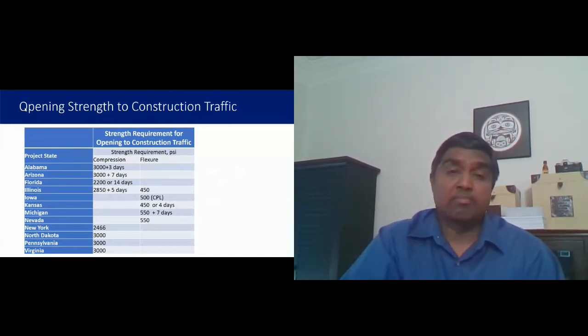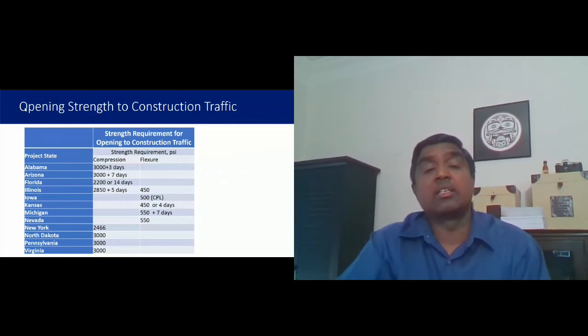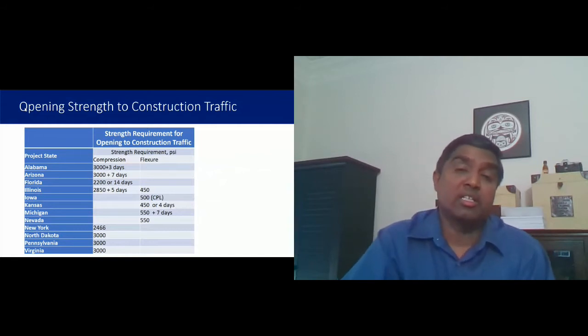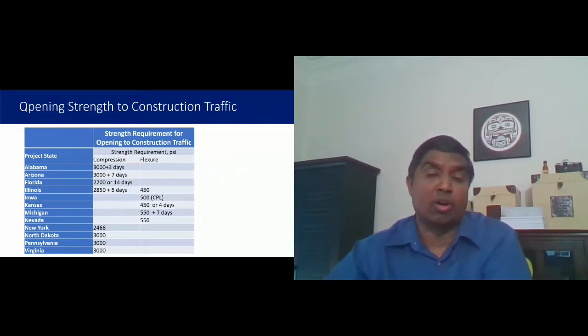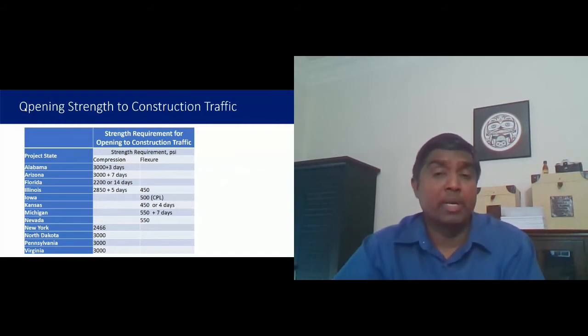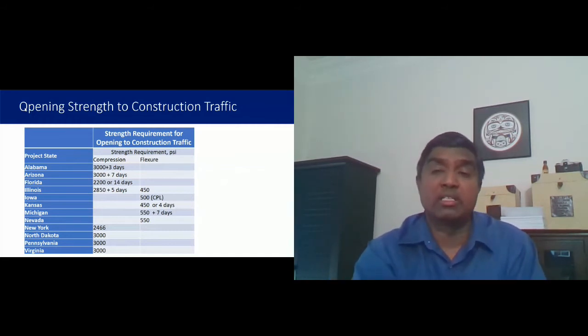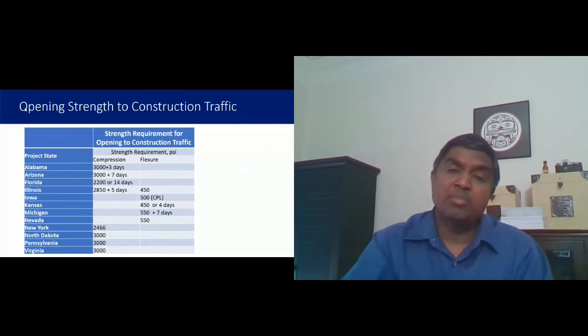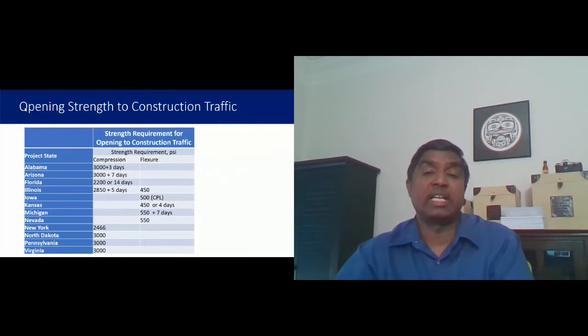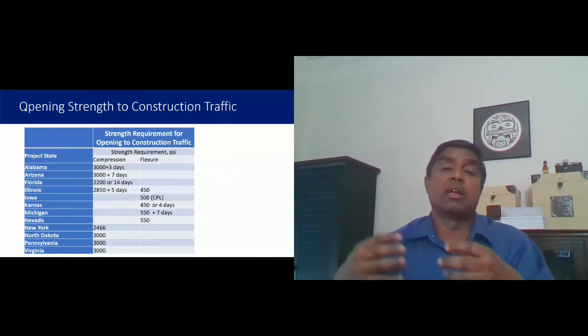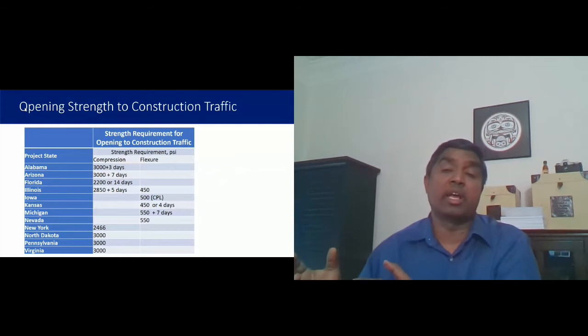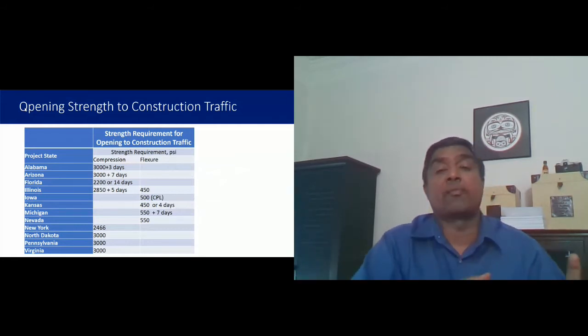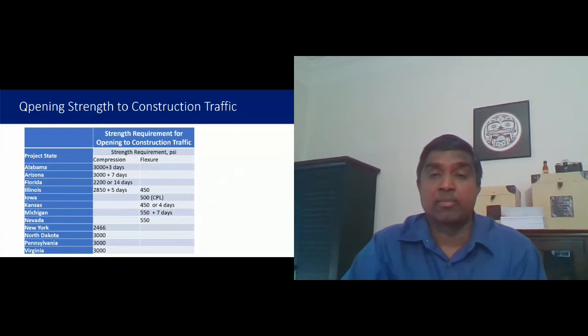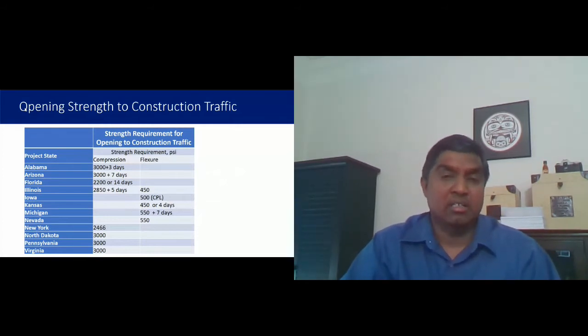Now, in most states, the strength is determined based on breaking either cylinders or beams that are primarily field cured. In some cases, people do use lab cured beams or cylinders, but most of the time it really is field cured cylinders. So the assumption here is when we break a beam or a cylinder, we are assuming that the beam strength or the cylinder strength would represent the strength of the in-place pavement or the structure, right? But is it really the case? The answer is no, because of a couple of reasons.